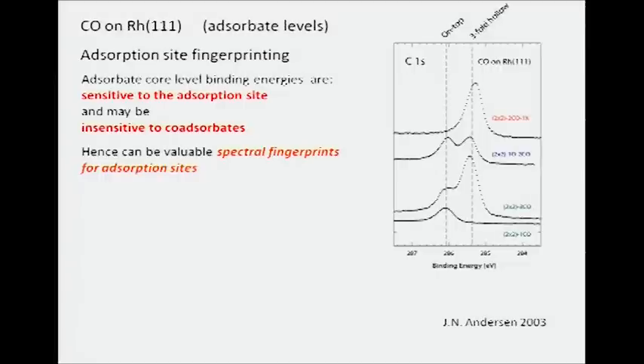And actually, if you co-adsorb with oxygen or with potassium, you see peaks at the same energies. And the conventional interpretation is that the CO initially adsorbs at low coverage in a top site on a rhodium surface atom, and that gives you this peak. And then at higher coverage, you start to fill in hollow sites, and you get this peak. And so this appears to provide a spectral fingerprint of the local geometry, which is of interest to me because my main interest is in surface structure determination.